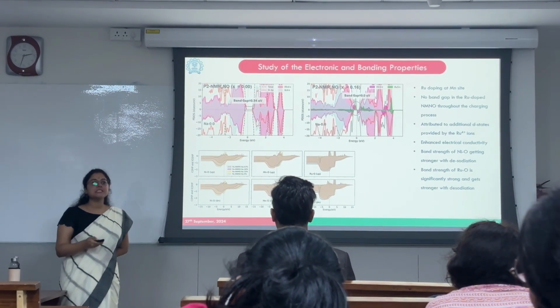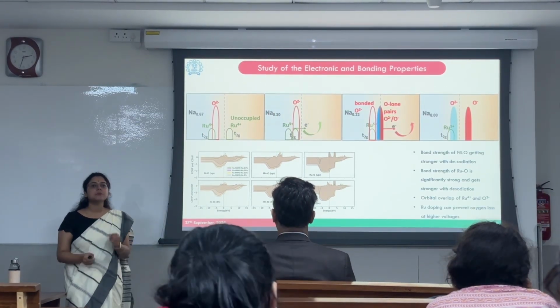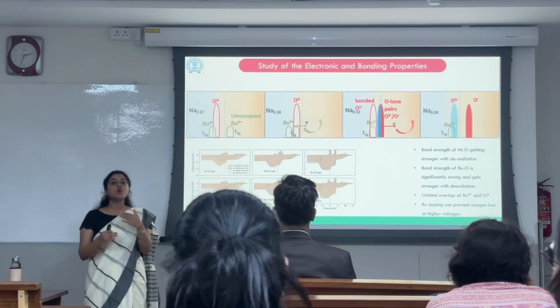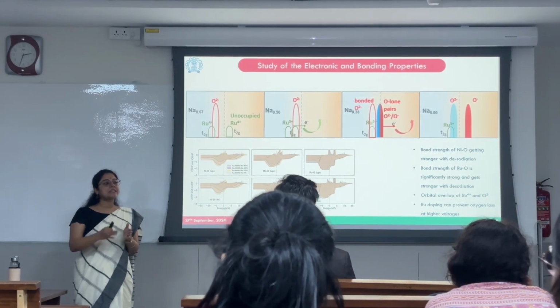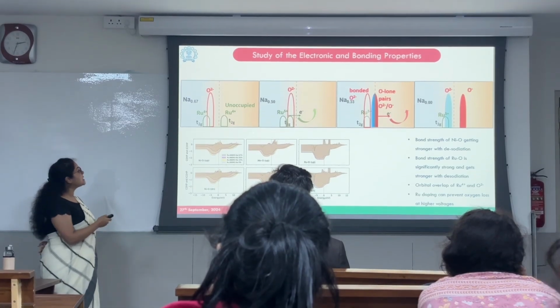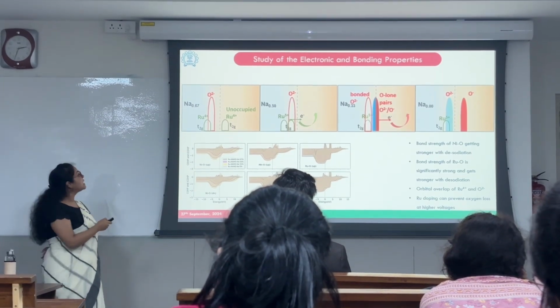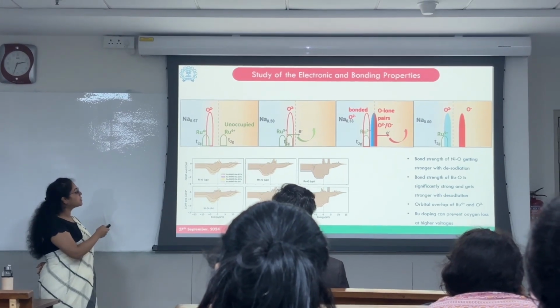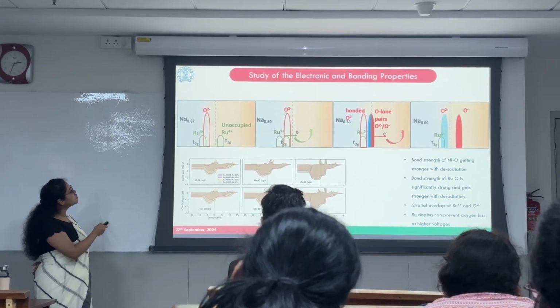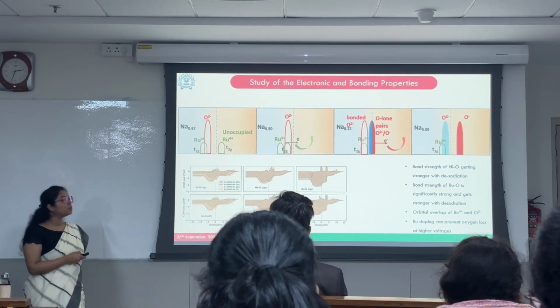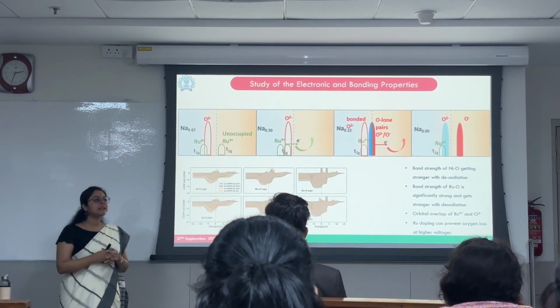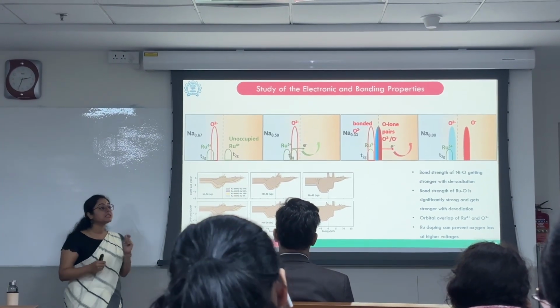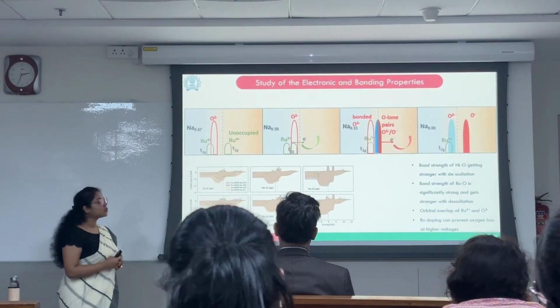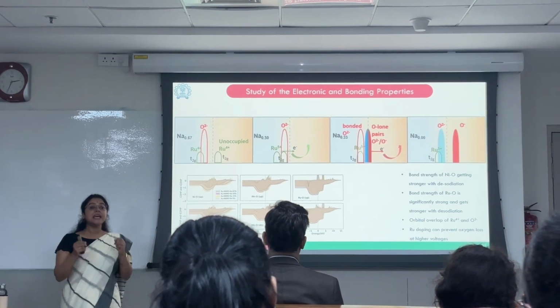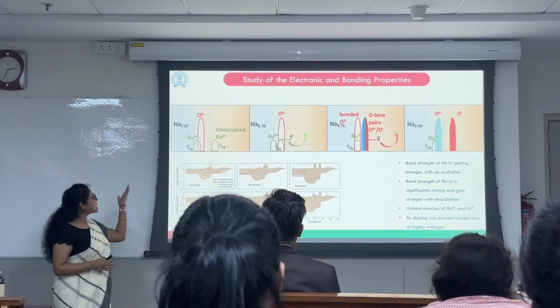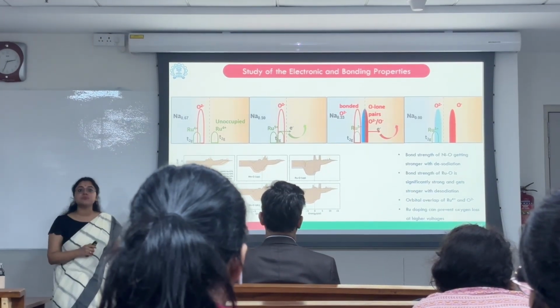We further analyzed the PDOS calculation of ruthenium and oxygen because the major criterion for anionic redox reaction is the overlap of the d orbitals of the metal and the sp orbitals of the ligand. It was seen that at the 0.67 state, which is the starting phase, through the band diagram we can see that ruthenium 4+ is successfully overlapping with O2-. And it is to be noted here that it is a myth in anionic redox reaction that it has to be alkali rich in order to conduct anionic redox activity. However, we have seen that in spite of being sodium deficient, with our starting composition at 0.67, we could still achieve the anionic redox reaction.